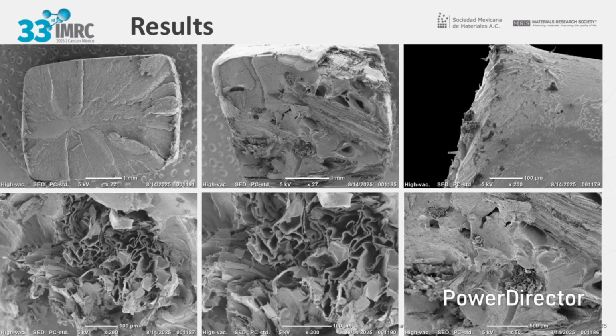1. The present micrographs show the general morphology of the fracture, low magnification, 22x, 200x. Lower magnification images show a heterogeneous fracture surface, where the polyamide matrix exhibits a radial crack propagation pattern characteristic of a brittle fracture mechanism. At the same time, partially adhered fibers are observed, as well as cavities resulting from the detachment of reinforcements, which constitute direct evidence of interfacial phenomena. The lack of uniform adhesion suggests limited chemical compatibility between the polyamide matrix and the lignocellulosic fiber, attributable to differential polarity and the presence of hemicelluloses, lignin, and surface waxes in the plant fiber.